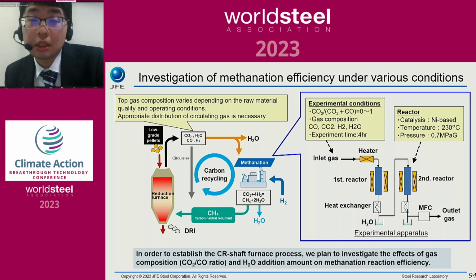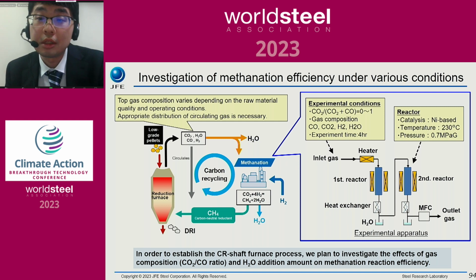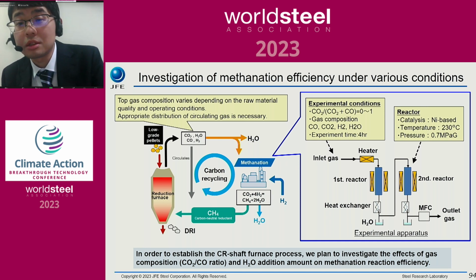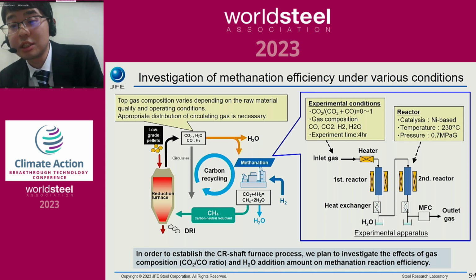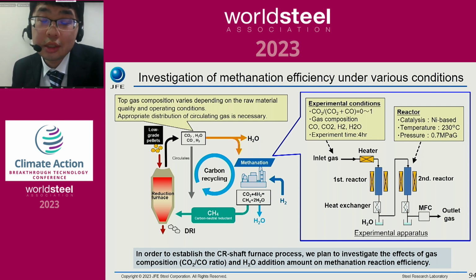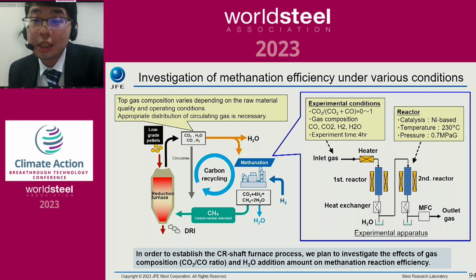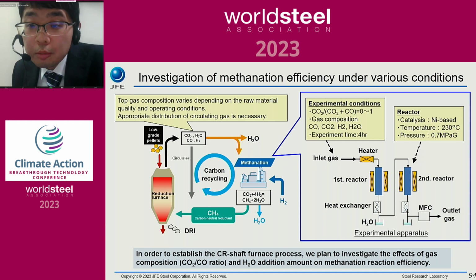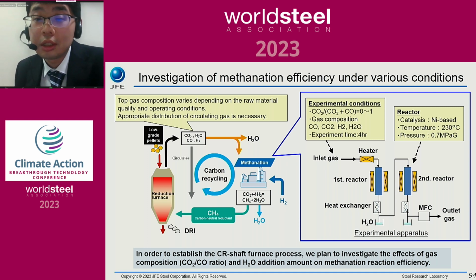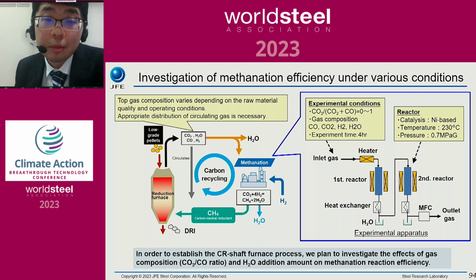The composition of the top gas of the shaft furnace varies depending on the operating conditions and the quality of the raw material. So it is necessary to determine the appropriate amount of gas circulation and gas distribution in the process. And in addition, depending on the condition of the methanation, carbon may deposit on the surface of the catalyst and reaction efficiency will decrease. So an appropriate amount of water is also added to avoid this.